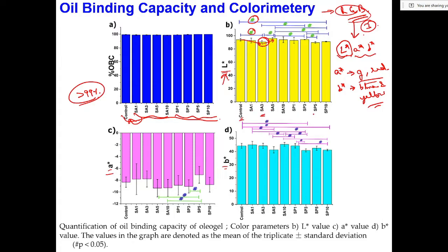In SP or the Span 60 based formulations, again if you see, at SP5 we had the lowest L star value. Okay. Then when we looked into these A star values, when it is negative, that means we have a green component. When it is positive, we have a red component. Okay. So over here, if you see the A star values, they were negative in nature. That means the green component was prevalent in all the samples.